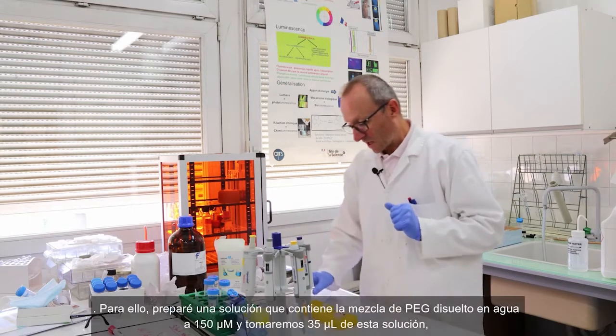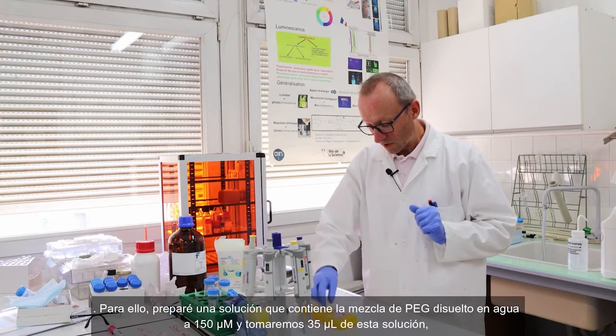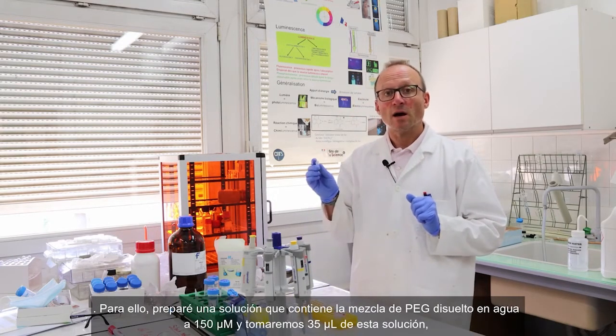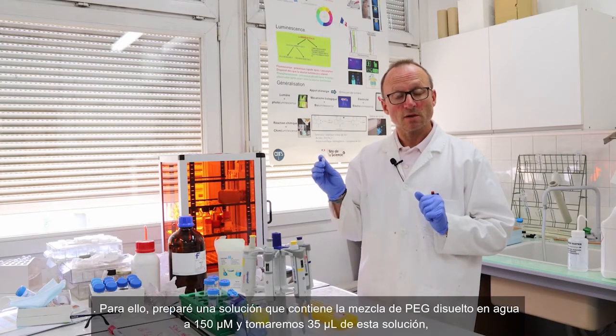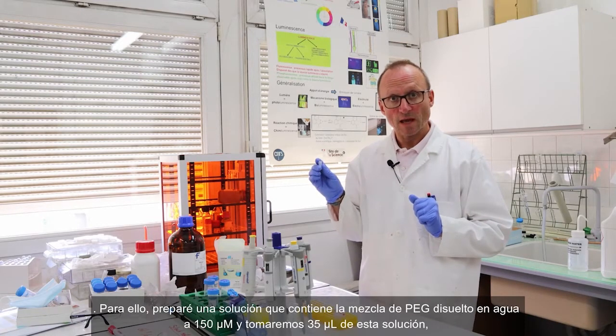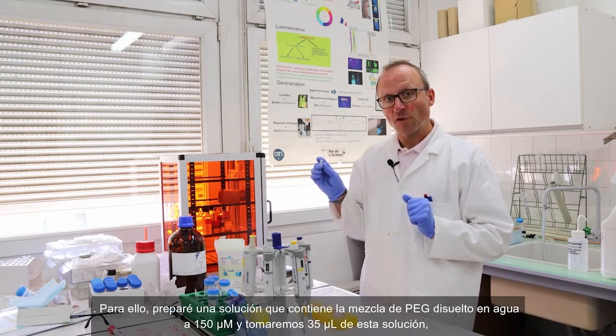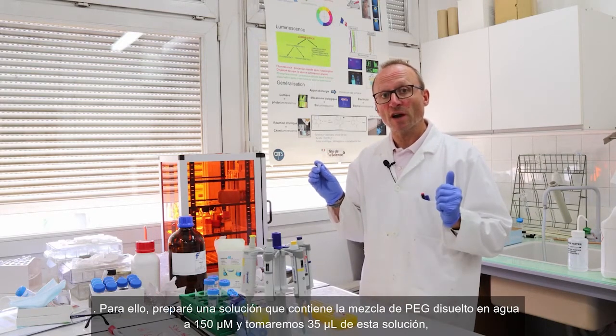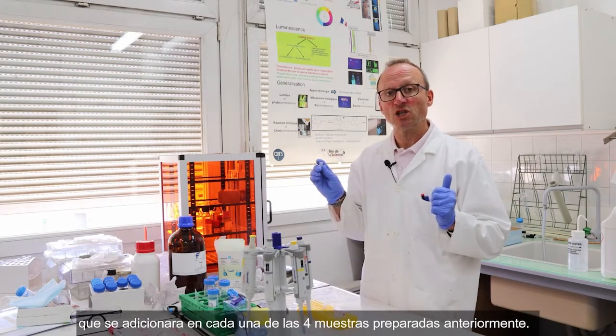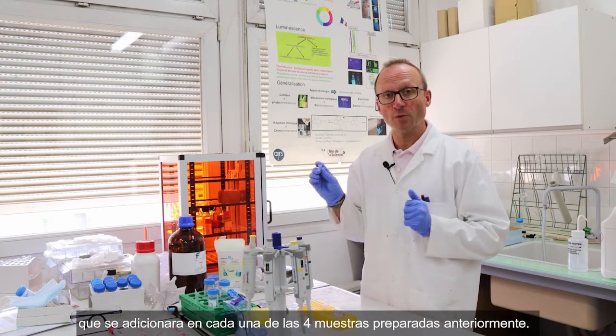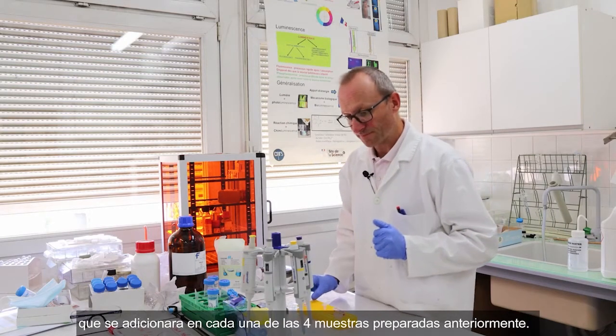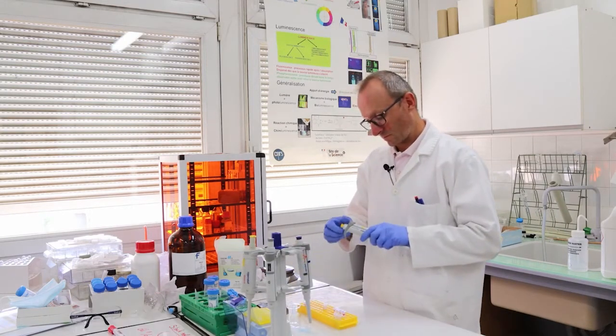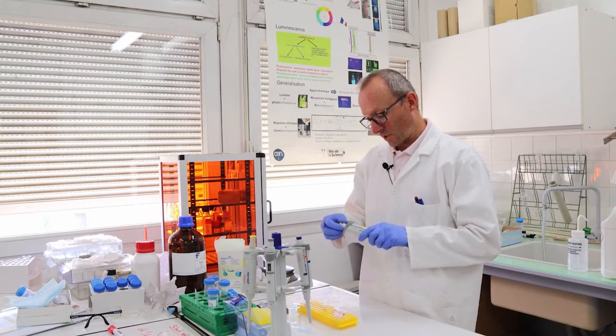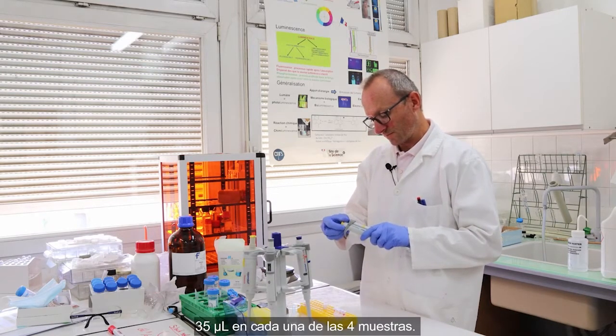So to do that, I prepared a solution containing the PEG dissolved in water at 150 micromolar, and I will take 35 microliters of this solution that I will add in each of the 4 samples I prepared earlier. 35 microliters.